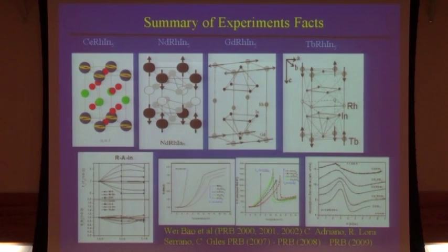But again, who determines the direction of the moment? Crystal field. So maybe by only changing the crystal field for cerium, we can understand why T_N decreases for cerium and not for the others. Okay, but in order to do that, we need to make some calculations to show that tetragonal crystal fields can act differently, because I showed it to you for a cubic, which is much simpler, but tetragonal is a little bit more sophisticated.